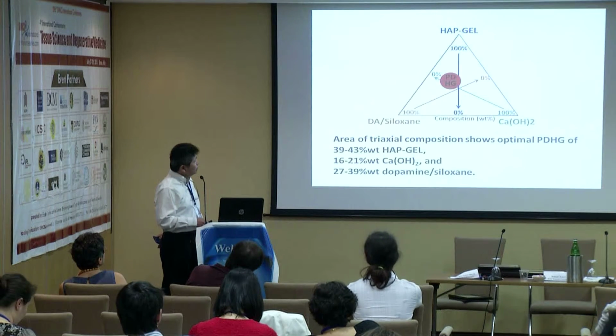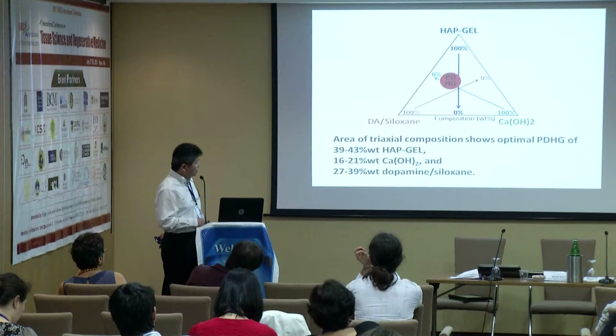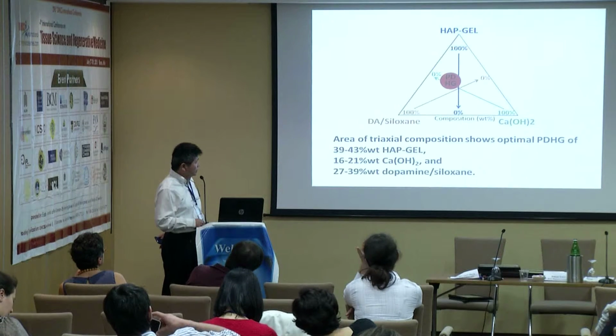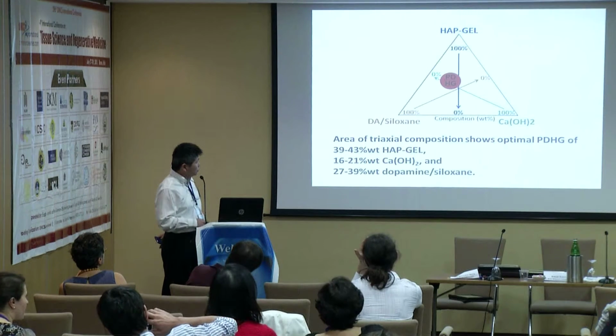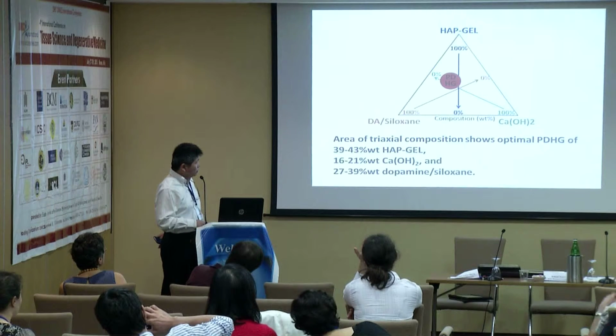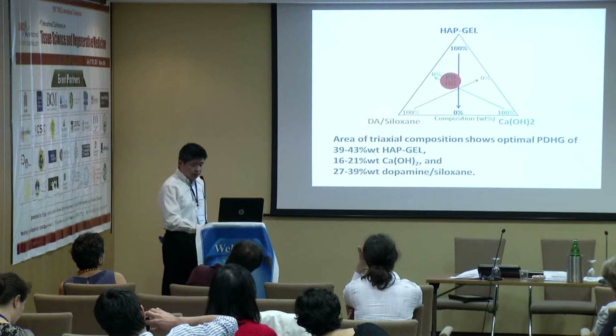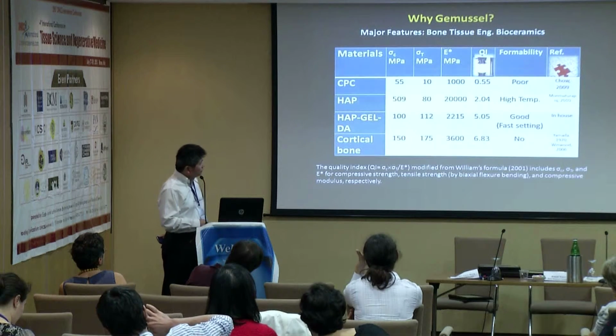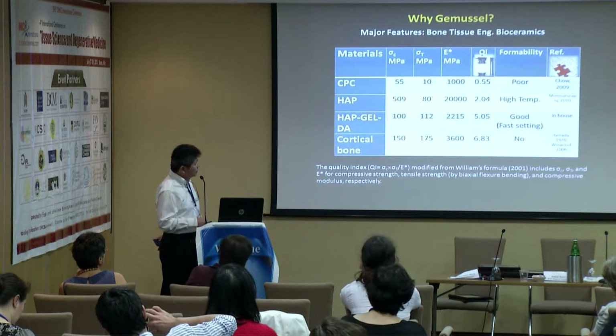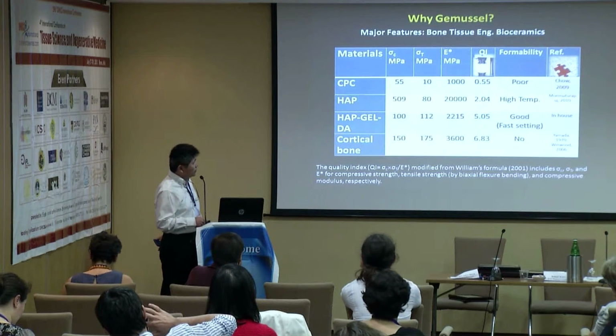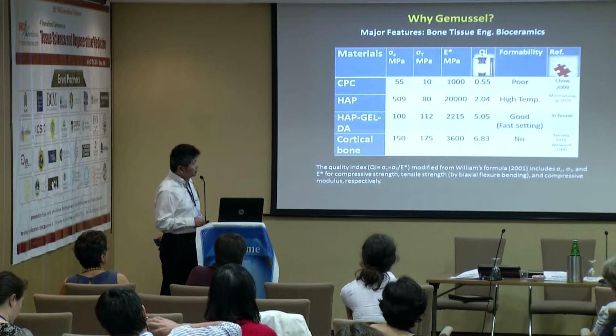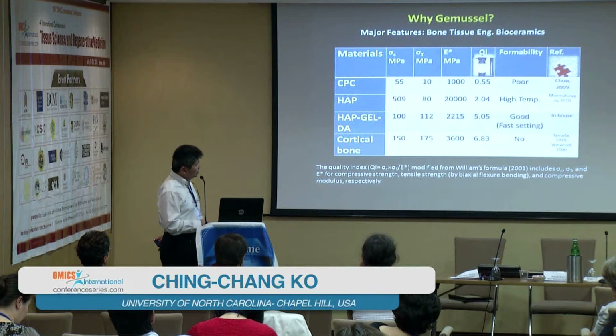And then we did some optimization to find out the best ratio in our current composite. It's about 40% of hydroxyapatite-gelatin particles and about 20% of calcium hydroxide, which requires about 25 to 40% of dopamine silane composite. And the final composite material, which we can show here, is about 5 for the quality index, which is getting closer to the cortical bone. Part of the reason is because we increased the compressive strength and also the modulus.